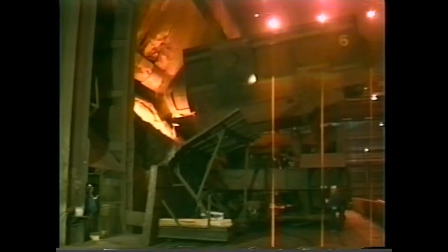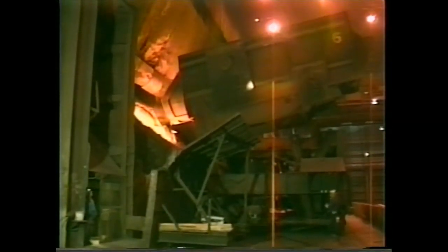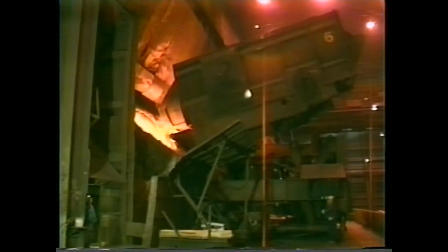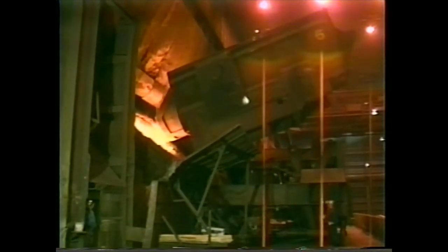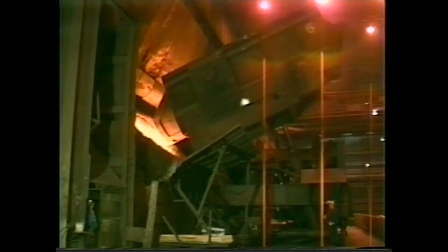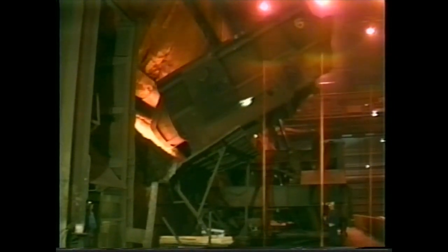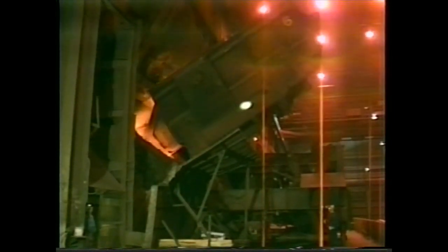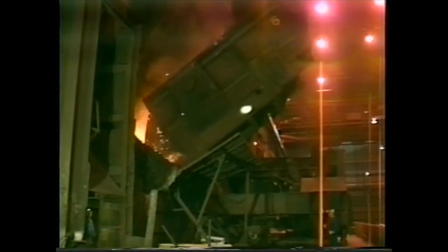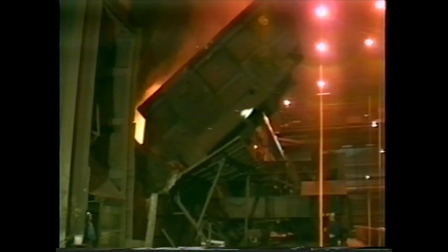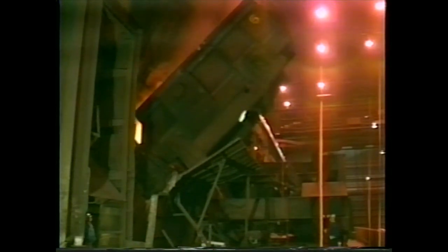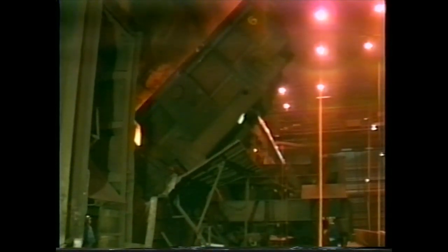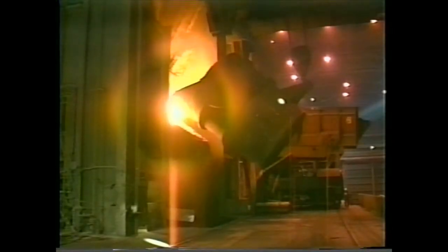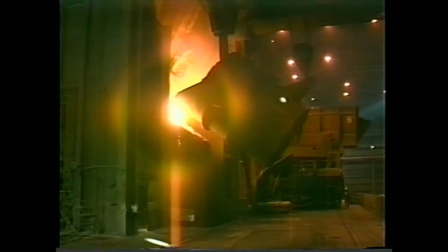The heart of the steel making process is the furnace. This is where all the elements are brought together after individual preparation to produce the steel specified by the sequence number. First, the scrap is charged into the furnace by the scrap trimmer. Scrap is used as a coolant to keep the metal temperature within a specified range during the oxygen blow. Then the charging crane operator charges the hot metal into the furnace. At this point, the charging is complete.